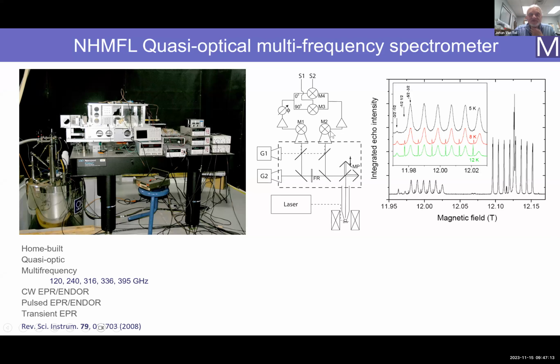And in many cases for CW measurement, we actually use the power that comes back in the same polarization that you send to the sample to one detector, and the cross polarization to the other detector. And then we mix these 2 signals back together, and this eliminates phase drift because all the path lengths are the same, and it eliminates a lot of phase noise as well. So that helps us in signal to noise for CW measurements.